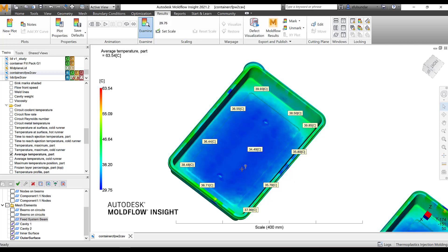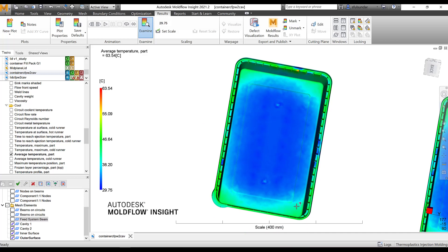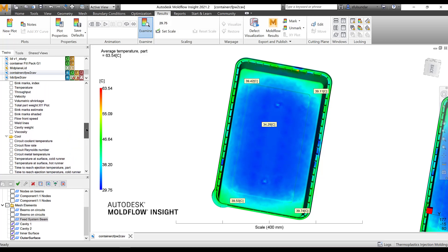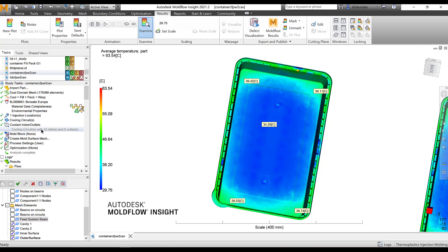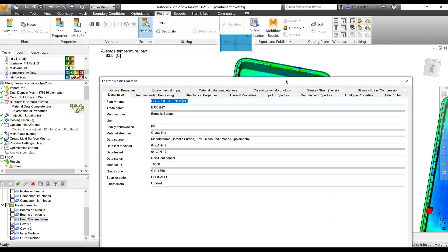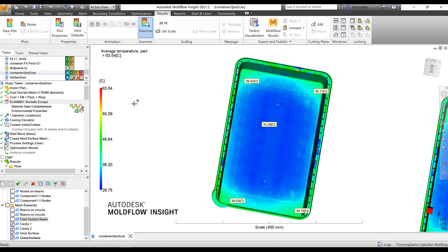We won't have an option of looking at what's happening at 7 or 8 seconds because this is a static analysis. If you want to know what's happening at 7 or 8 seconds you need to run a transient Cool FEM analysis. From the core side temperatures are pretty much in the range of 35 to 40. To interpret whether your cooling time is sufficient, the maximum part temperature shown here — 63.5 — should be below the ejection temperature. The ejection temperature can be found in the recommended processing; in this case it's 122, so I have an opportunity to reduce the cycle time from 15 seconds to perhaps 11.